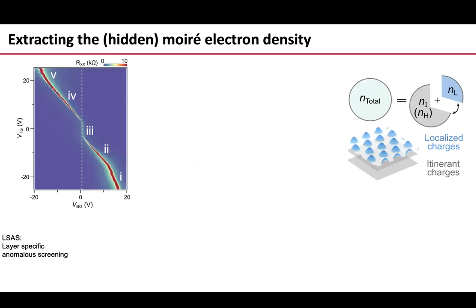So what is happening in that region three, okay? Over this range, between these two corners, over that range of top gate voltage, what we're doing is adding charge to the system. It's not that the gate is not working. We're adding charge to the system, but it's all going into the localized system. And that's why transport looks identical as we vary the top gate in that range, because the itinerant system is the same. We're just adding charge to the localized system, okay?